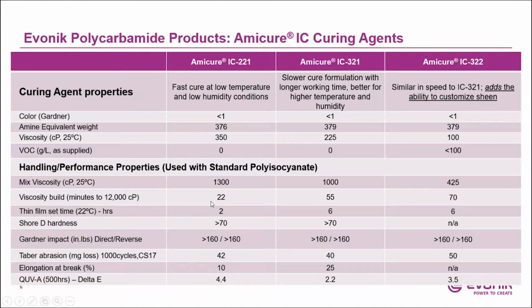Viscosity build, so what we're talking about is viscosity as it builds in the bucket after you mix part A and part B together. Again, a lot of times, after you mix the two together, you're not going to be keeping the material in the bucket. You are going to pour it out on the floor and start the application. But the viscosity build, as you see, 221 is faster, so you get 20 minutes to 12,000 centipoise. With 321, you have 50 plus minutes, and 322, you have about 70 minutes to 12,000 centipoise.